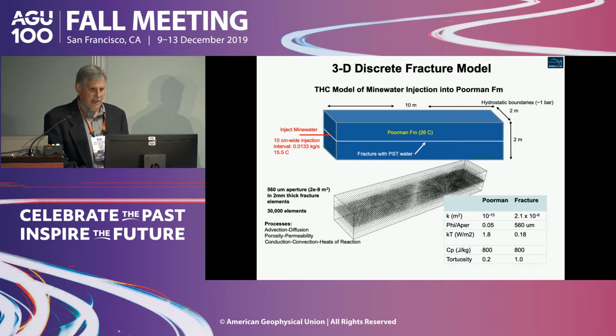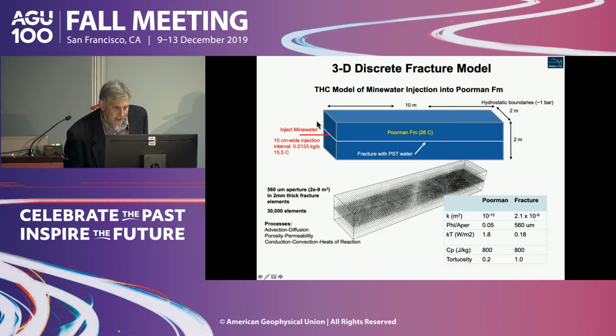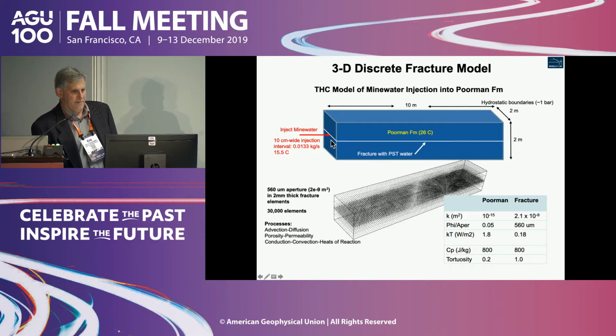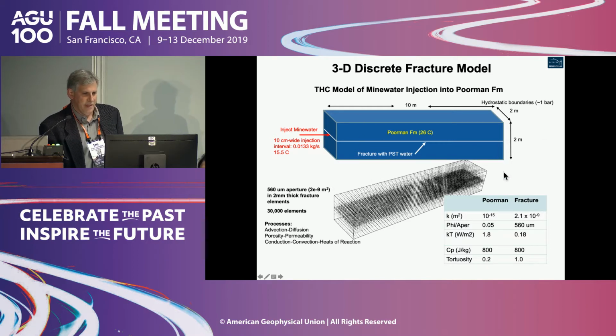So what does the model look like? In this 3D model, there's a thin fracture here, and it's actually about 2 millimeters, but with some rock in it. So it's about a 500 micron fracture, so half a millimeter, a fairly permeable fracture. And then it's surrounded by matrix and very finely gridded all around. This is about the scale between drill holes, about 10 meters or so. Permeability is about 10 to the minus 15 for the rock matrix of the Poor Man, and pretty high for the fracture, 10 to the minus 9 meters squared.